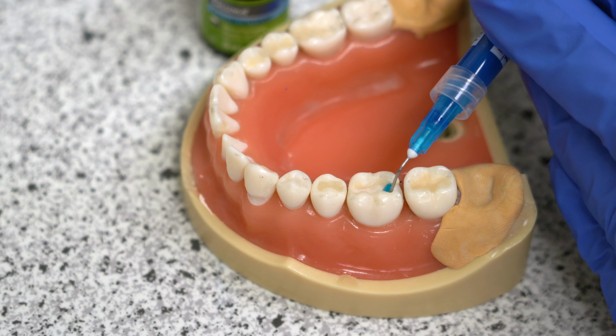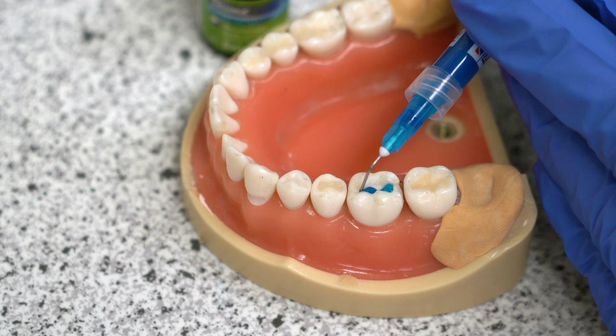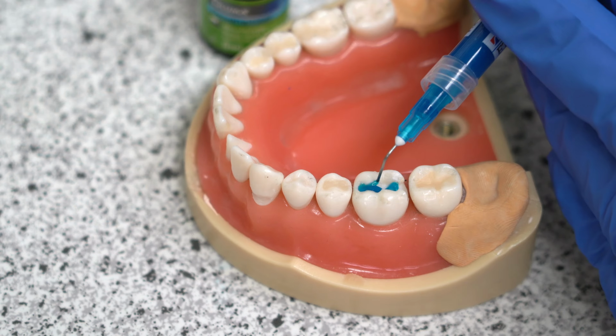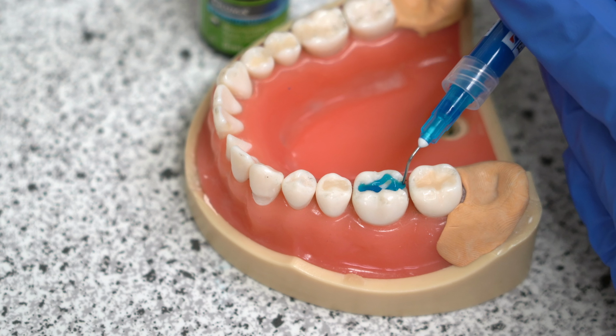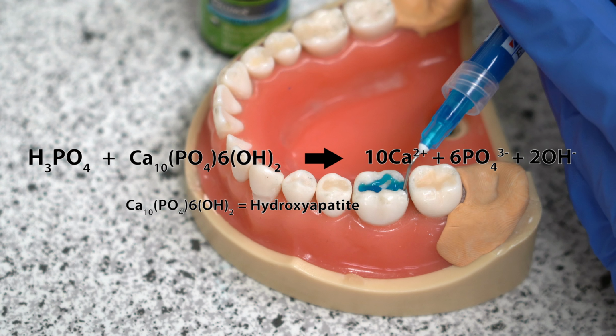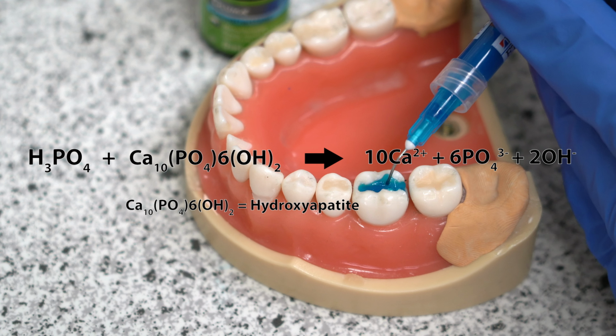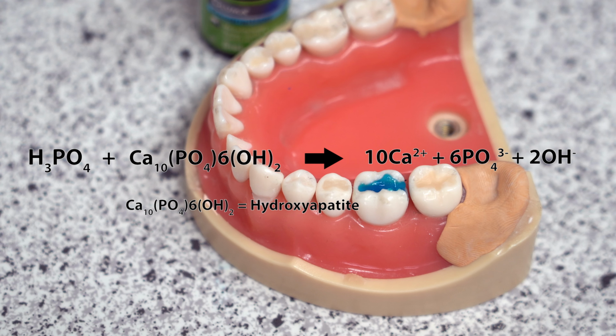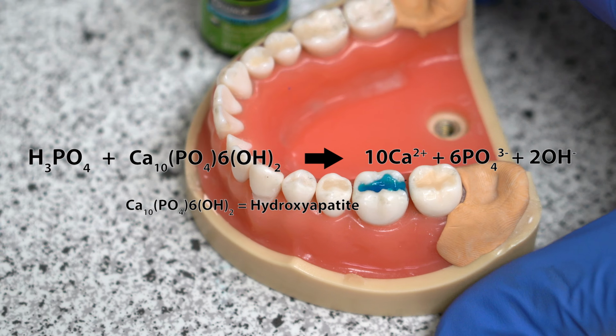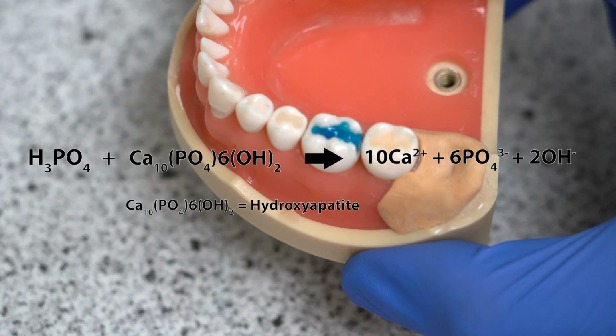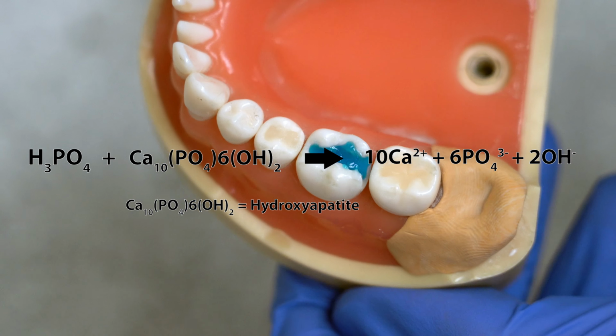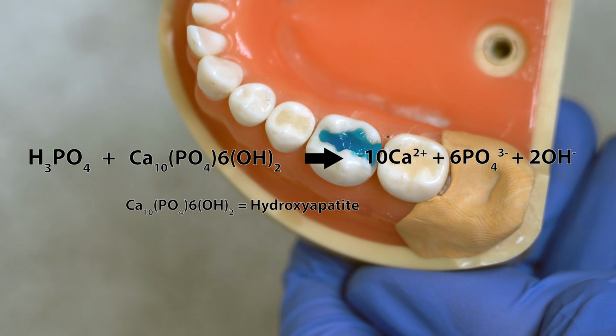The resulting structure of the tooth resembles a honeycomb pattern, greatly increasing surface area. Second, it increases the negative charge on the enamel surface and facilitates the chemical reactions of MDP adhesives and hydroxyapatite to produce more calcium salts, thus improving the chemisorption between enamel and the adhesive.